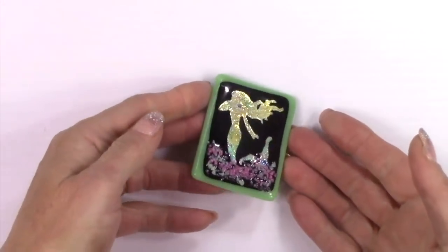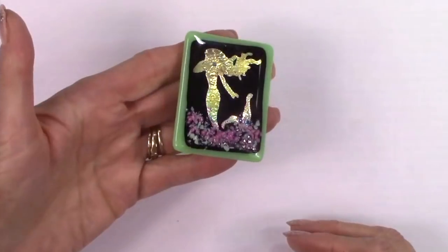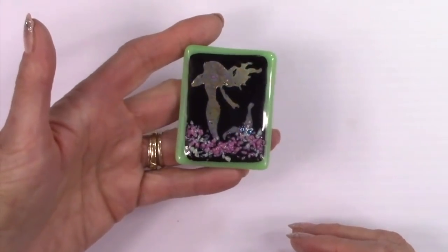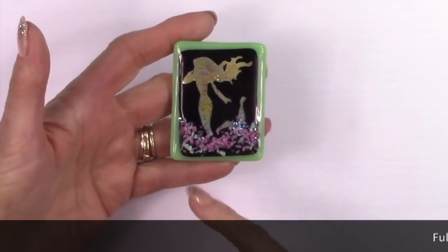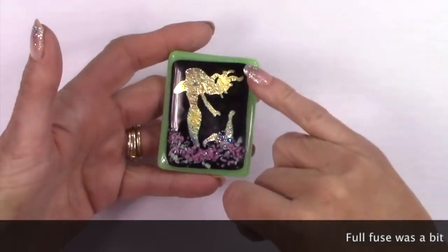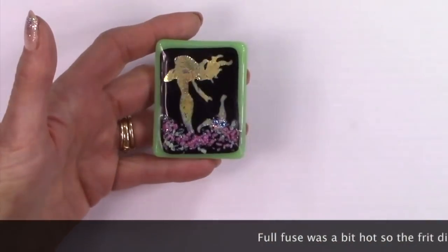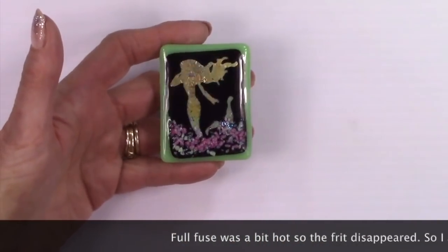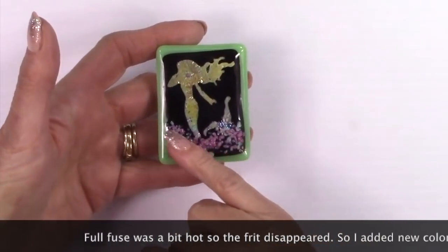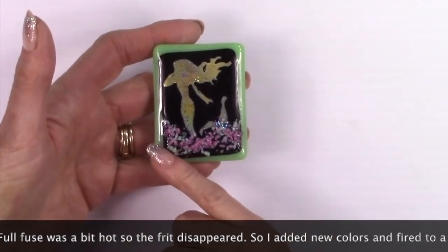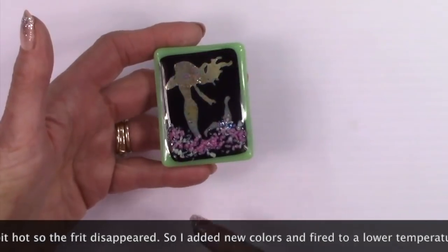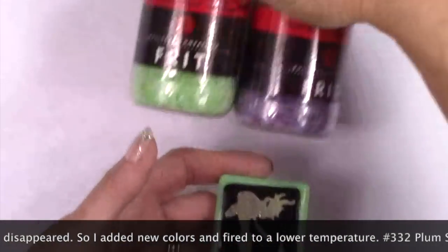Okay, our mermaid's out of the kiln, and I actually fired it twice. The first time I fired it, the Frit that I chose first fused too much. I fired it to a full fuse, so it fused too much, and it was sort of transparent, so it disappeared. So what I did was put new Frit on there.